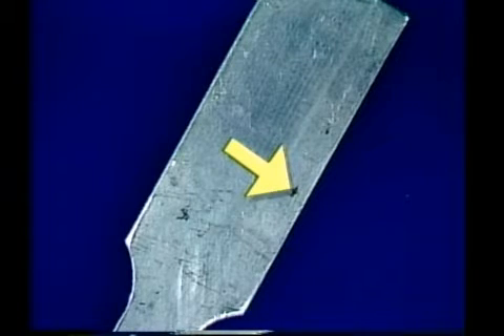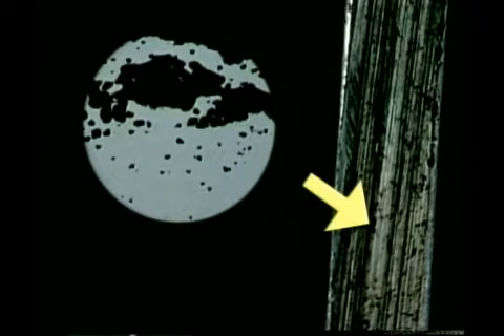The surface shows the bubble effect. When sectioned, the presence of the subsurface voids is evident, which is shown here. These subsurface voids can be structurally detrimental to the part and can only be detected by metallographic examination or ultrasonic inspection. The condition is aggravated by the presence of certain furnace atmosphere contaminants, especially sulfur, and by prolonged high-temperature exposure in a contaminated furnace environment. It may be alleviated by employing moisture-free atmospheres or volatile fluoride-containing salts.